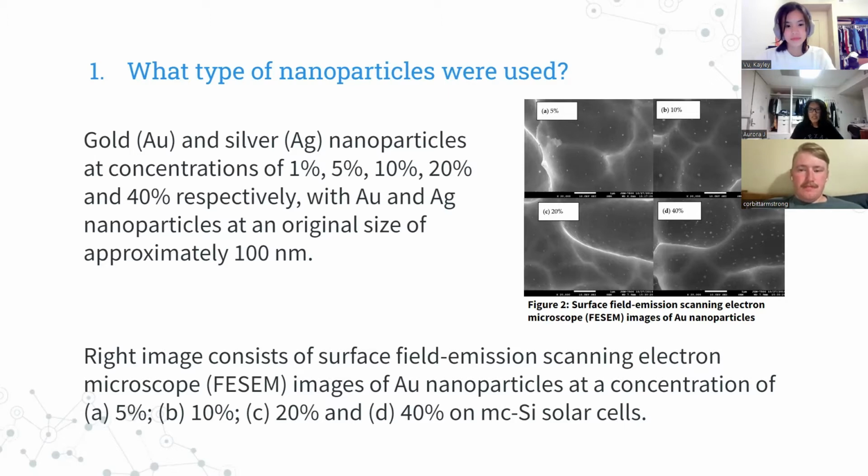However, after spinning/annealing, some nanoparticle sizes will agglomerate to larger nanoparticles at sizes of around 100 to 250 nanometers. This verifies that broadening the shape of the resonance wavelength is caused by random distribution and the non-uniformity of the size of the gold nanoparticles, which causes the particle density to increase with the gold nanoparticle concentration.